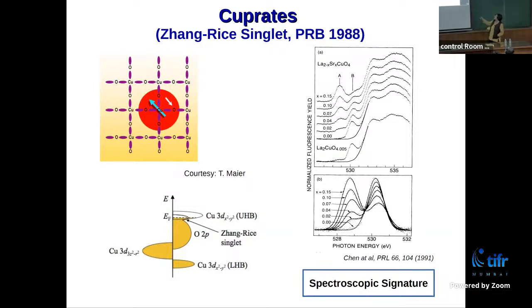And the evidence of such a thing is actually a spectroscopic signature. If you do an oxygen K-edge spectroscopy, Kalu is not here, he is an expert on it, you see actually a pre-peak, and this pre-peak grows as you are doping more and more, saying actually the holes you are putting in the system, instead of going to copper, are going to oxygen.